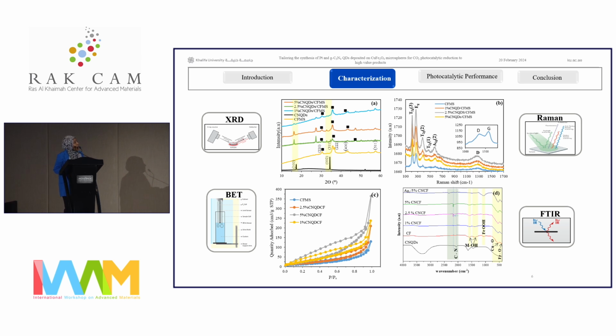And then in the Raman, we observed the Raman modes assigned to copper ferrite and the D and G bands related to graphitic carbon. Then in the BET, we found that as we increase the loading of the quantum dots, we increase the surface area of the nanocomposite as well. And finally, in the FTIR, we observed the vibration modes for copper ferrites in the fingerprint region, and the CN bond assigned to the graphitic carbon nitride. And we noticed that as we increase the loading, we increase the intensity of the CN bond.